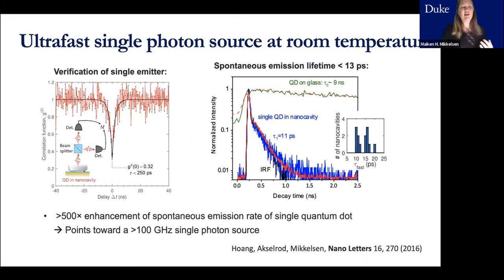Another area where fast spontaneous emission is very important is ultra-fast single photon sources. If we're not at the single photon level, we have the choice of using lasers if we want fast modulation. For quantum information science, we have to stick to single photon sources. So the only way we can enhance that speed is through the Purcell effect. And in this case, we're using a similar sample geometry, but just using a lower density of quantum dots, such that we on average have a single emitter under each of these cubes.